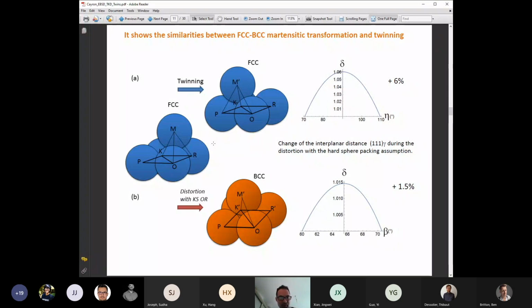But if you look at the orange representation, it means that you change the position of the atoms exactly as in twinning, but at the same time you open the angles in the 1-1-1 plane. The 60 degrees angle in the 1-1-1 plane, you open it to 70 degrees at the same time. You move the atoms. Then what you have is exactly the FCC to BCC transformation. And okay, you can calculate, for example, how the atoms move perpendicularly to the 1-1-1 plane. You can do a lot of calculation with that.